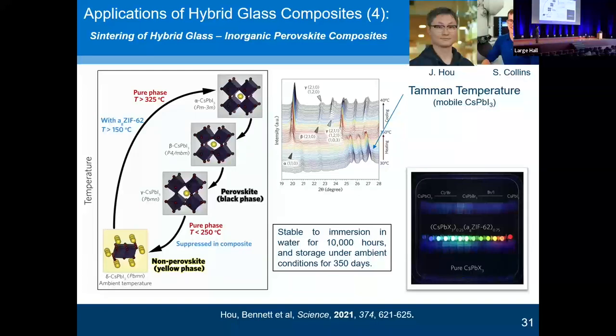In this case, we've chosen cesium lead iodide, the perovskite. At room temperature, it's in a yellow phase, a non-perovskite phase, and only at high temperature do you see conversion to a cubic photoluminescent system. Same trick, melt it with a MOF glass, and instead of it reverting to its room temperature non-perovskite phase, you trap it in one of these photoluminescent black phases, and you can play around with the chemistry to make these beautiful photoluminescent glasses here.